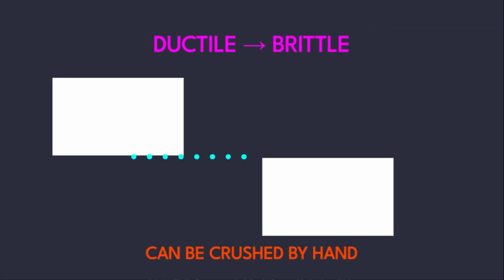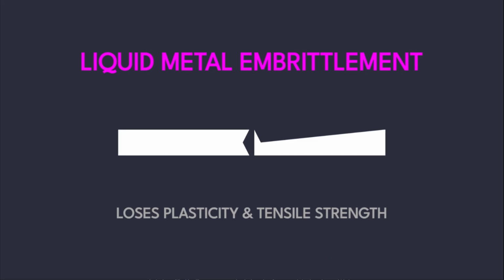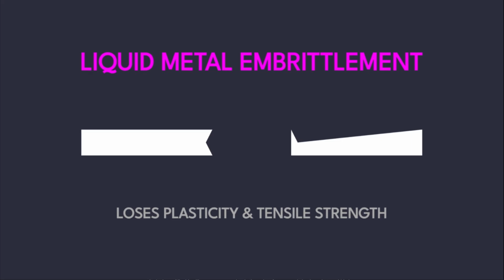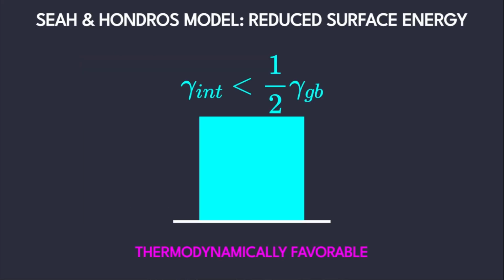The gallium atoms effectively act as a lubricant at the atomic scale, replacing strong aluminum-to-aluminum bonds with much weaker interactions. This specific type of intrusion transforms a ductile metal into a brittle substance that can be crushed by hand. The phenomenon occurring here is scientifically classified as liquid metal embrittlement. This is a specific form of environmental degradation where a normally ductile metal loses its plasticity and tensile strength when exposed to certain liquid metals.